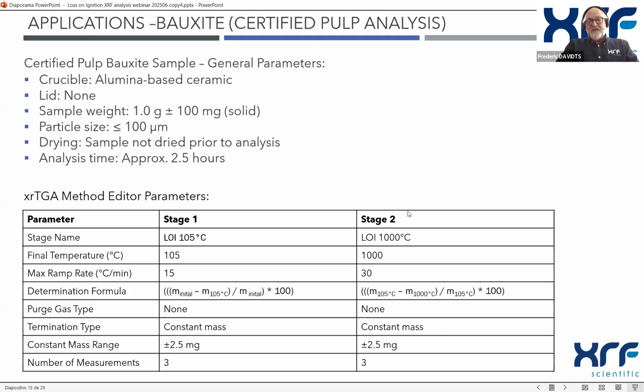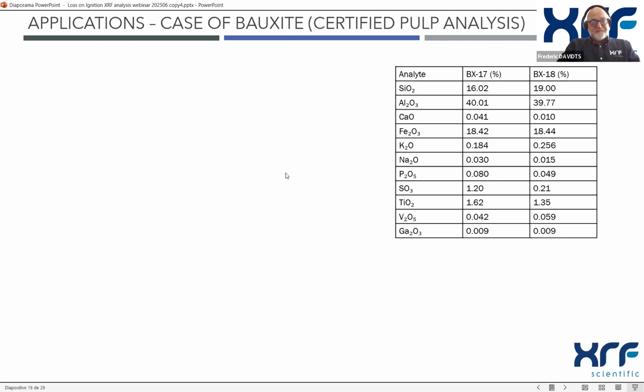Then we do the LOI stage at 1000 degrees, and we can speed up the heating ramp a little bit. After that, the same determination to reach the constant mass. So we check 3 weighings to see that we are still in the range of plus or minus 2.5 milligrams. And for the calculation, of course, we calculate the loss on ignition in dry mode, meaning the weight after we have dried the sample.